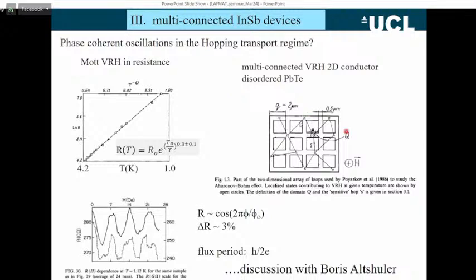And what his group did was they evaporated lead telluride onto a grid system. And so it opened up holes in the system. It was multi-connected. And he was able to measure phase coherent oscillation. So as charge in this system went around the grid, it would interfere, and the interference would be driven by the magnetic flux in the grid. So he demonstrated very nicely that his devices went over to hopping.